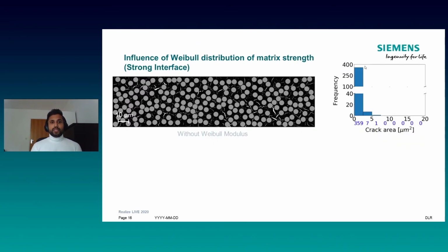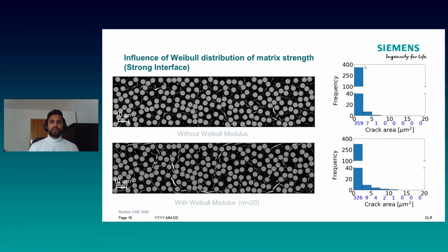Now when we compare the results, we have a bigger volume, but still without Weibull modulus, we still see small cracks present in the matrix, about 360 cracks in the region of 2.5 square micrometer. And as soon as we introduce the effect of Weibull modulus, we see a trend towards the block formation which we are expecting from our material.